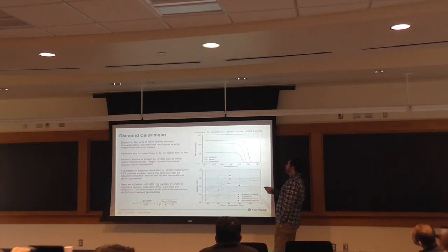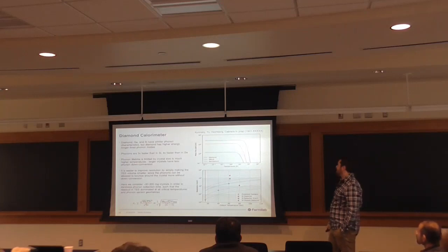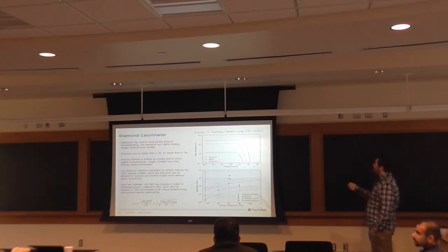And this mean-free path increase really comes not from a scattering rate change, but from a velocity change. So these are faster phonons, and therefore, even though they have the same scattering rate as silicon or germanium, they can make it further. So it's intrinsic, no? You are comparing the intrinsic germanium? Intrinsic, yeah. And in the paper, I didn't do a good job of updating.